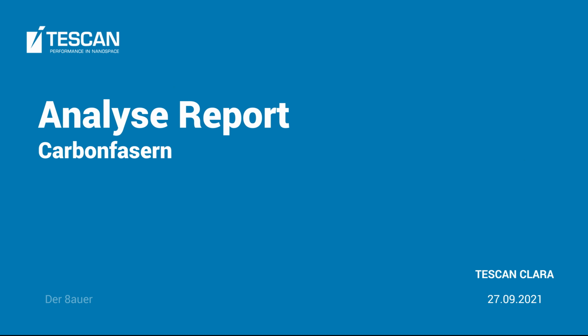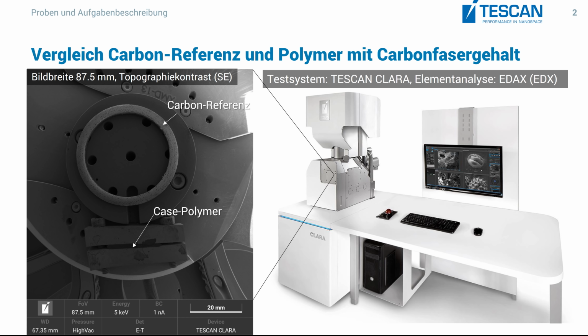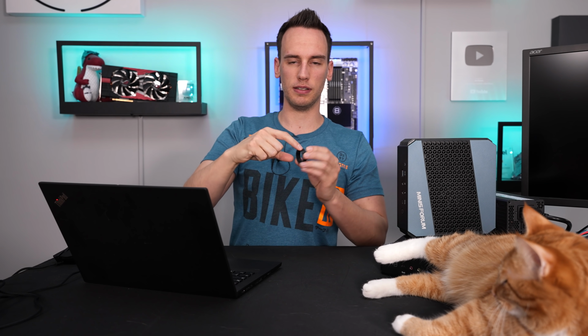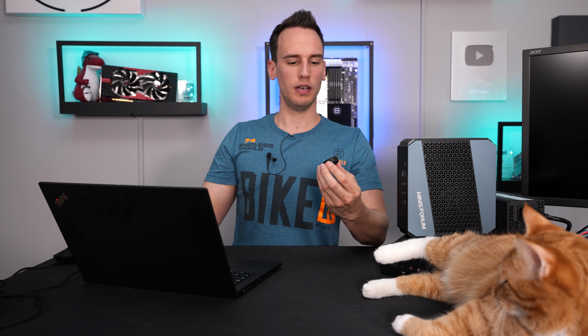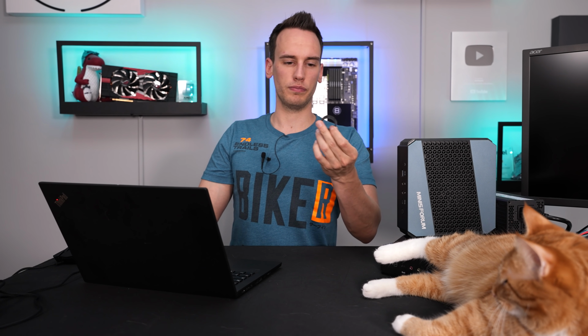Anyway, if you switch to the second page of our analysis, on the left side you can see an image of the chamber. Inside the chamber, on top you can see the carbon reference, so that's our ring, and on the bottom you can find the case polymer specimen. On the right side this is just an image of how the Tescan Clara looks, the SEM with the EDX built in. EDX is basically using electrons that hit the surface, and then you have some X-rays being emitted from the surface, and this way you can determine what kind of atoms the part is made of.